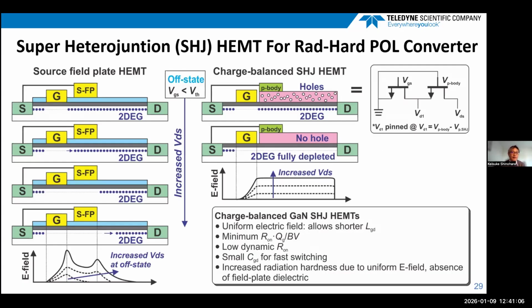And on the left, it shows how the two-dimensional electron gas depletes with increasing drain voltage at off state. In the source field plate devices, the 2-DEG is laterally depleting with increasing drain voltage. And when the pinch-off voltage of the source field plate kicks in, the 2-DEG under the field plate is depleted. And then the 2-DEG keeps depleting laterally with increasing drain voltage, which results in the peaky electric field as shown on the left bottom. The electric field laterally expands while the peak electric field at the corner of the gate and the source field plate peaks at those locations.